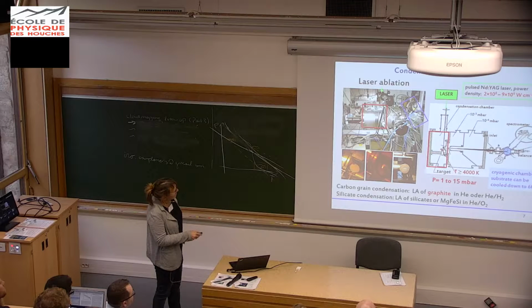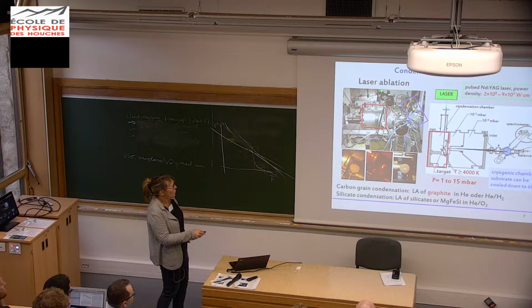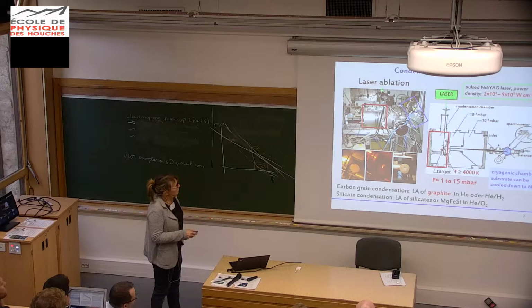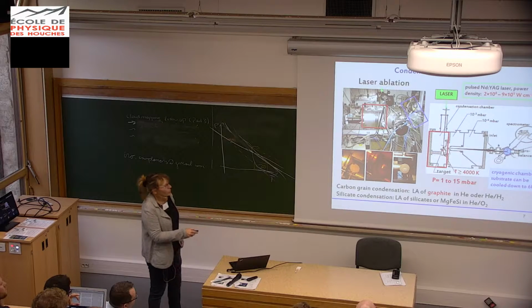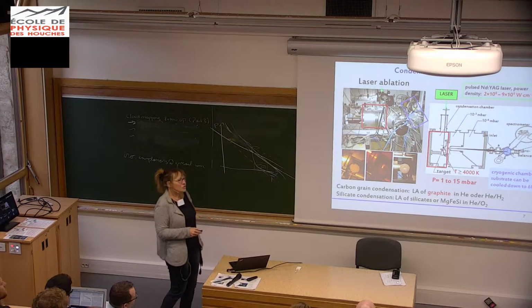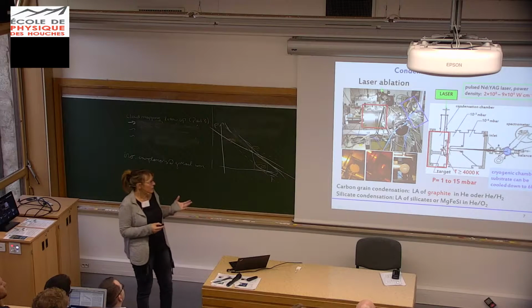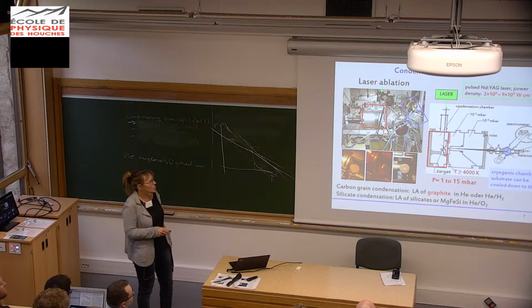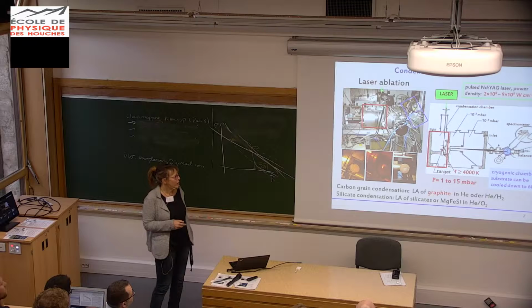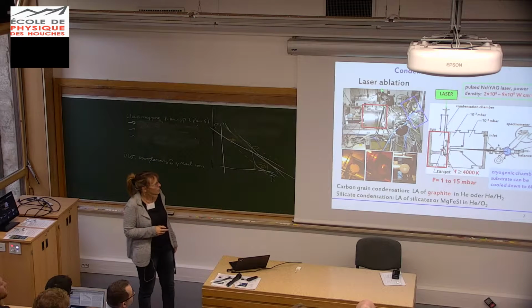You can see here the target is rotating, and the laser hits the target and evaporates the material, forming a kind of plume. So the target is here, and this is the ablation chamber. The pressure in the ablation chamber is between 1 up to 15 millibar, but normally we work up to 4 or 5 millibar, very low pressure.